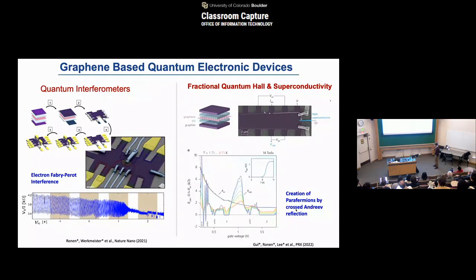In this way, we can make a close connection between this quantum Hall edge state and the superconductor, which allows us to proximitize the quantum Hall edge state with the superconductor, and we start to see a negative signal appear, which is an indication of so-called crossed Andreev reflection. Again, I'm not going to dwell on the physics here, although it's very interesting. I simply show you these two examples, where we can repeat something done in gallium arsenide very comfortably in the graphene device, or even more, rely on the two-dimensionality and semi-metal property of graphene.